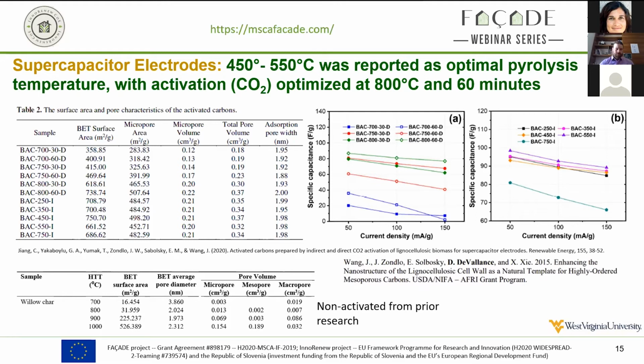If we look at table 2, you're seeing these surface areas go up quite a bit compared to what I was showing before. The one below where it says willow char was from the previous result. You can see at 800 degrees C in that original research, we were at 31 or 32 square meters per gram. Under this activation route, if you pick one of the 800s, the BAC-800-30-D, surface area is at 618. So quite a huge increase in surface area. And that ordered structure also translates to higher capacitance. You're getting capacitance up around the 100 range compared to the 40 that we were getting before.